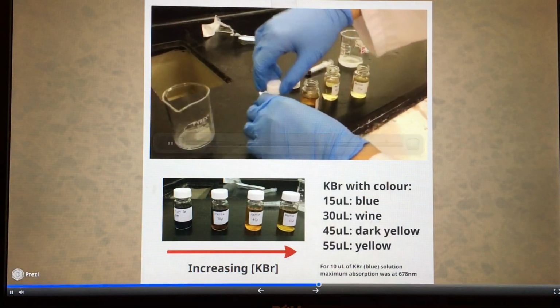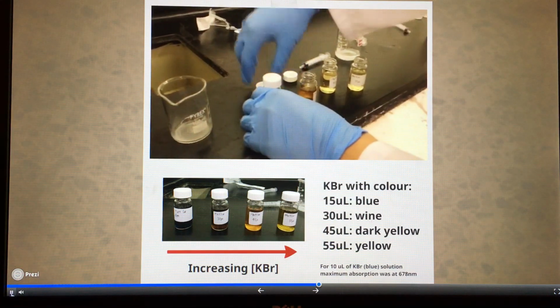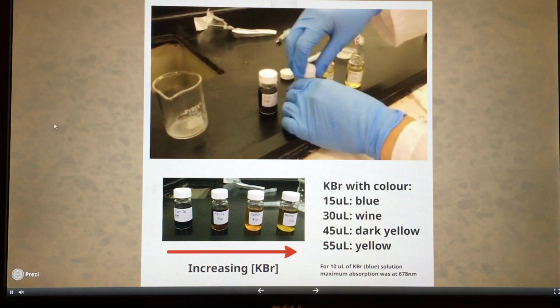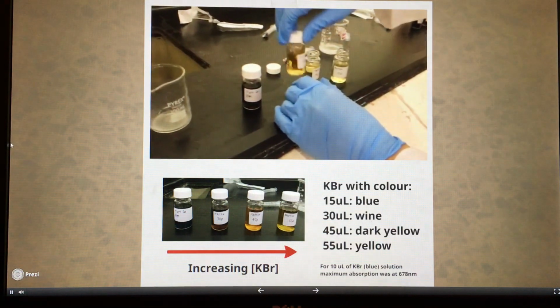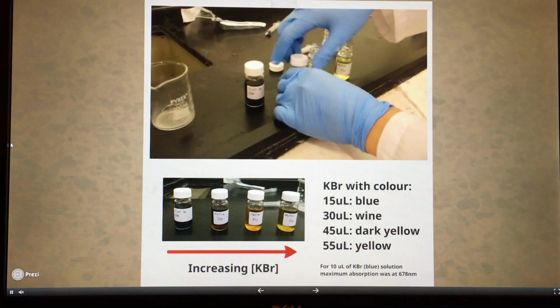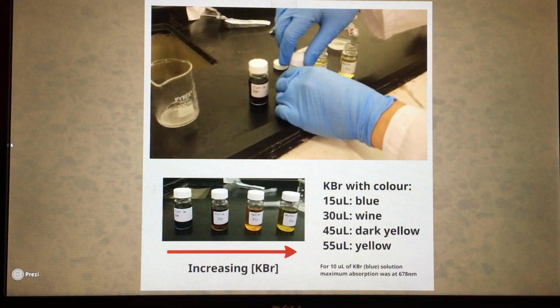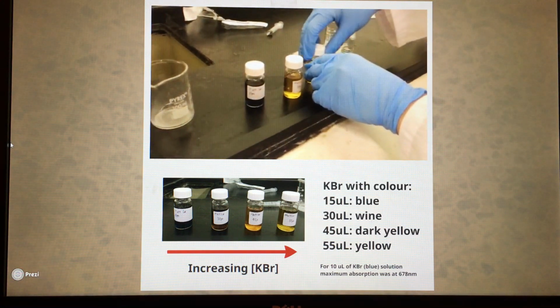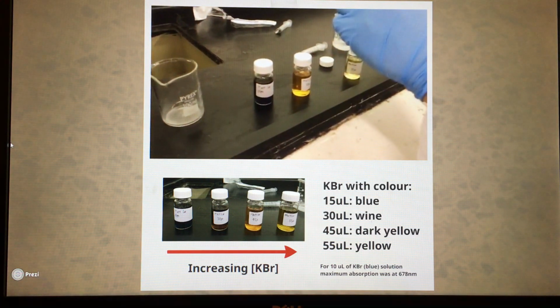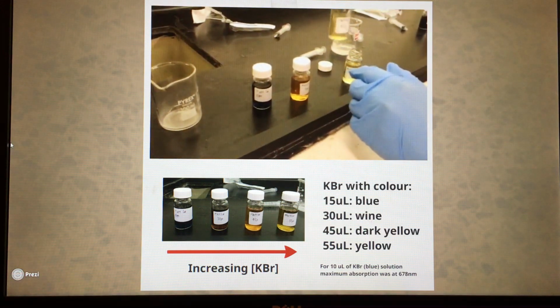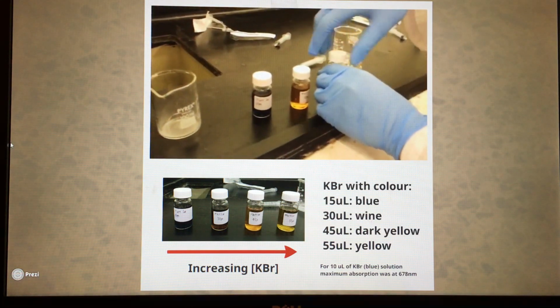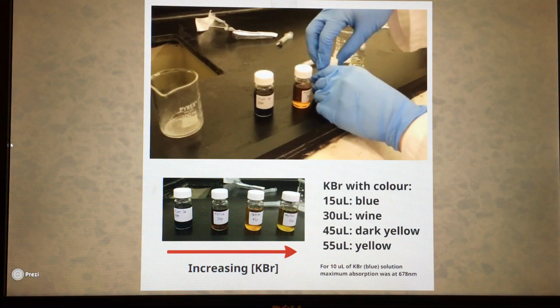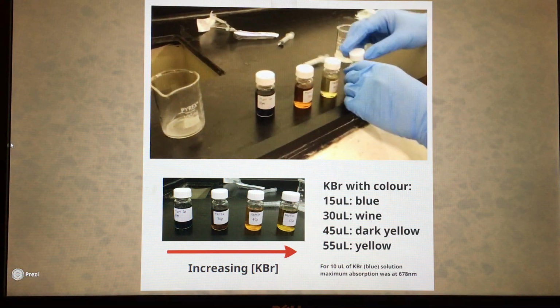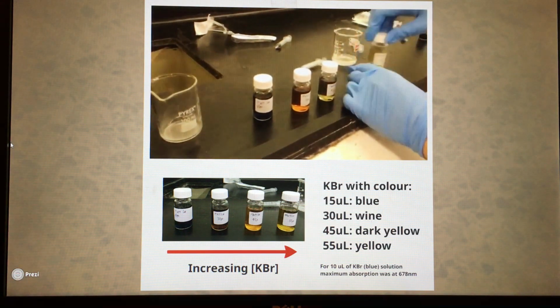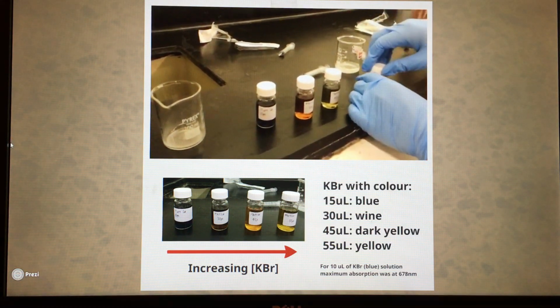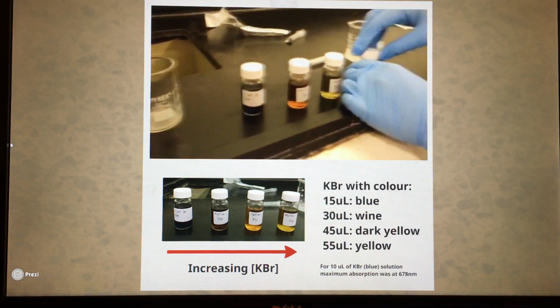As seen in the video, the color of the solution went from blue to yellow with increasing concentration of KBr, potassium bromide, which corresponds to smaller nanoparticles. Solutions with 15, 30, 45, and 55 microliters of KBr resulted in blue, wine-colored, dark yellow, and lighter yellow solutions respectively as shown in the picture. Using UV spectroscopy, we found that a blue, 10 microliter KBr nanoprism sample had maximum absorption at 678 nanometers, its complementary color red.